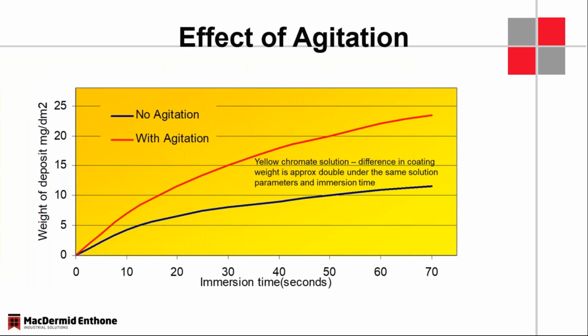And you can see that that goes directly towards film thickness. For yellow chromate solution, the difference in coating weight is approximately double under the same solution parameters and immersion time, simply because you're changing over that interface between the part itself and the Passivate solution that it's immersed in.